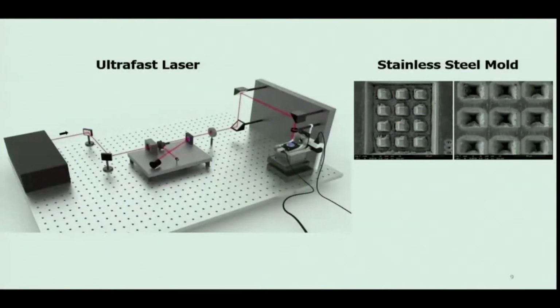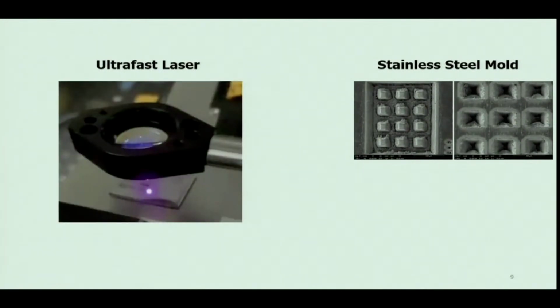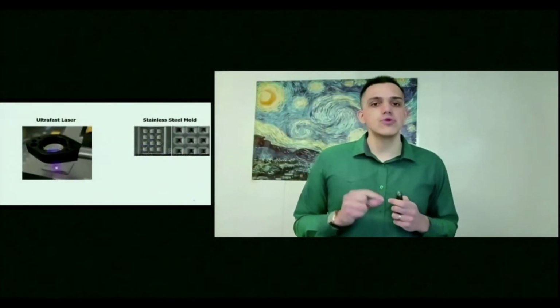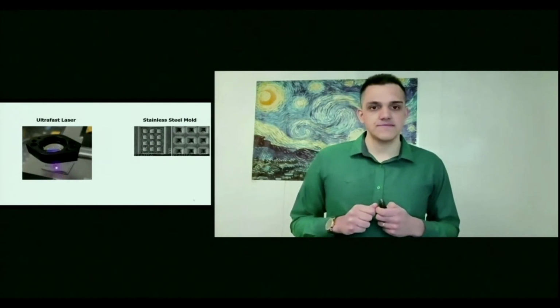In my project, I am using an ultra-fast laser to create these hierarchical structures in a stainless steel mold. In simple terms, the beam produced by the laser precisely blows out my metal mold, as you can see in this image, to create the structures that I programmed. And the purple light is the spot where the beam is removing material. Ultra-fast laser micromachining can effectively create surface patterns on the micro and nanometer scale by using algorithms through Python software. And in order to figure out which sizes for each geometry and their formats will provide the best outcome in terms of superhydrophobicity, I have to do computational thermodynamic optimization.